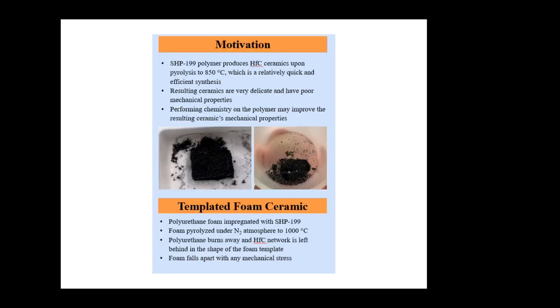Upon pyrolysis to 850 Celsius or above, the polymer turns into an HfC ceramic material, which is a simple and fast process. However, the resulting ceramic is very delicate. Here, I show a preliminary experiment that I conducted using a templated foam technique. I impregnated a piece of polyurethane foam with the SHP-199 polymer. At high temperatures, the polyurethane burns away, and the HfC ceramic is left behind in the same shape as the foam template. Any mechanical stress applied to the ceramic caused it to crumble.